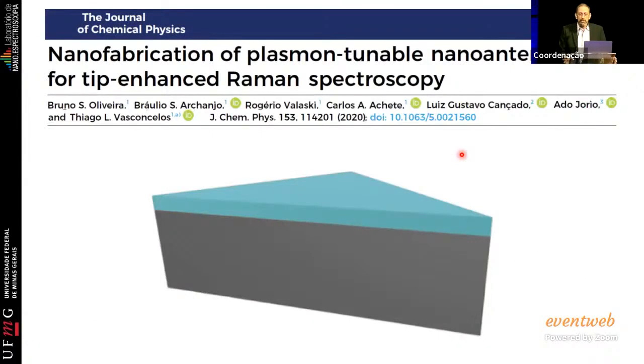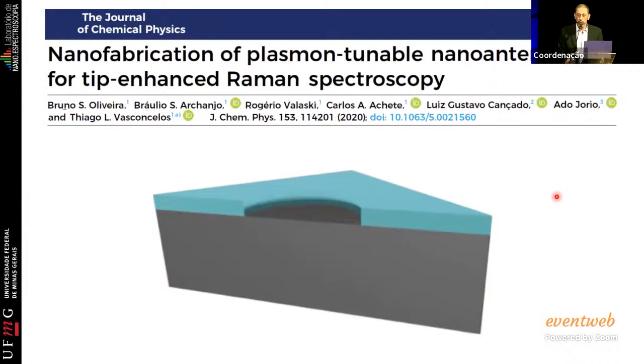So, and one other technical aspect is how to build such an antenna, and you build it using very well-established silicon technology, okay? So designing things in silicon is what the previous industrial revolution gave us, all the semiconductors, all the computers and everything. So you have a silicon wafer, and the silicon wafer has a silicon oxide cover, and then you open a hole and you throw an acid, and the acid will corrode only the silicon, not this silicon oxide. And the corrosion will happen following the crystalline structure of the silicon. So this happens, nature gives you that.